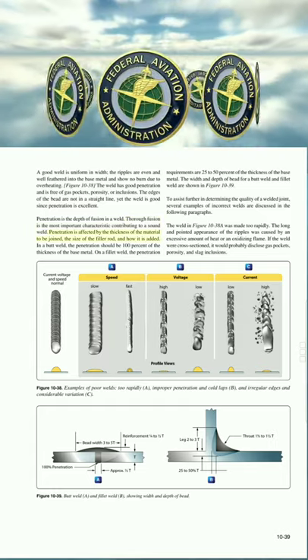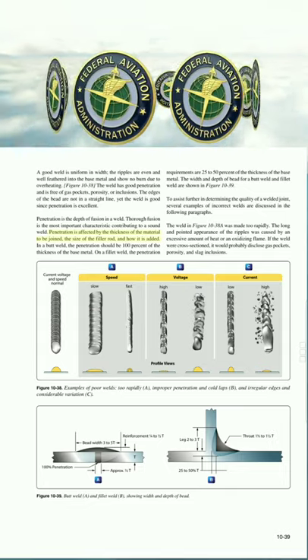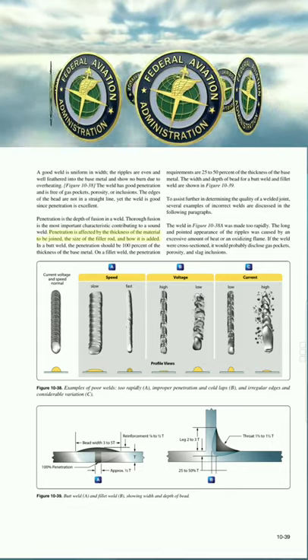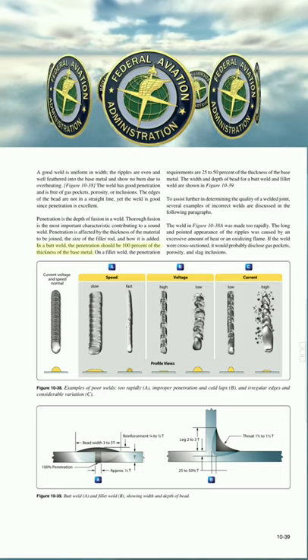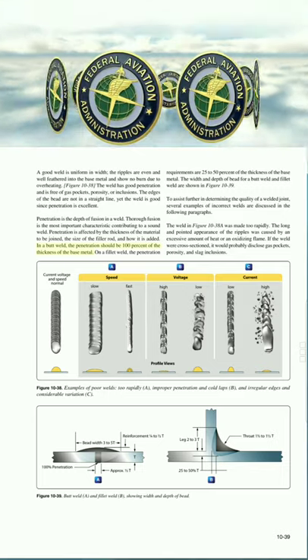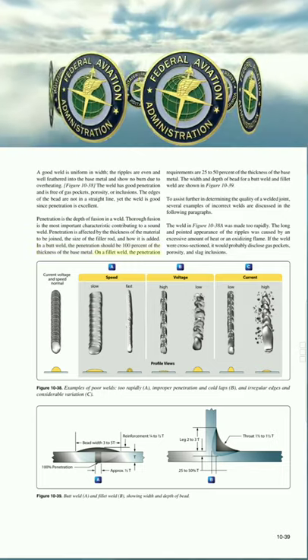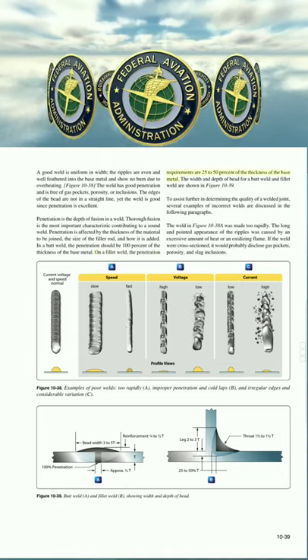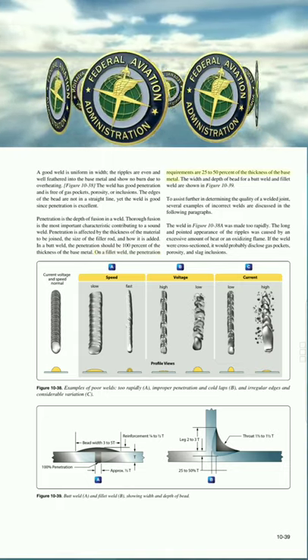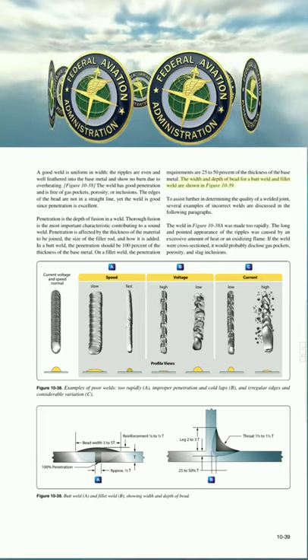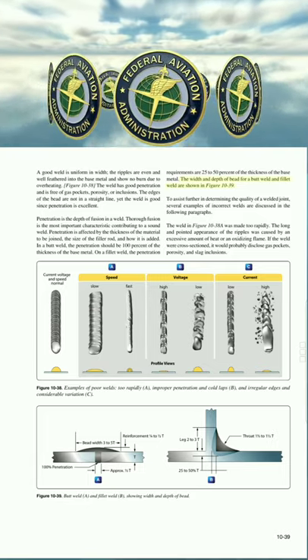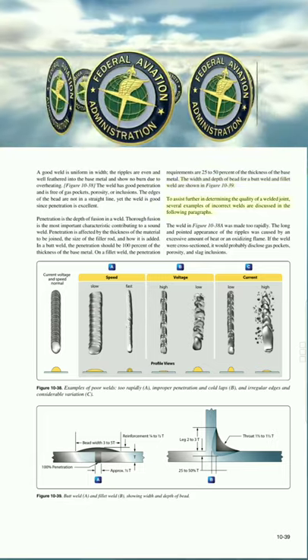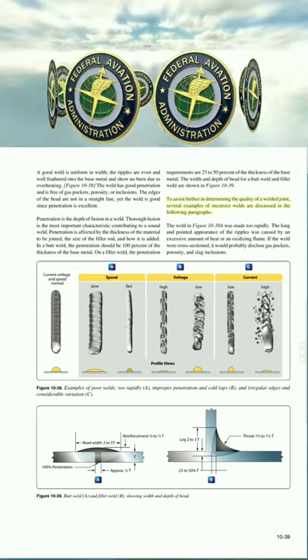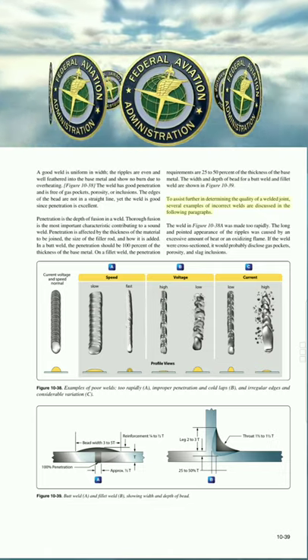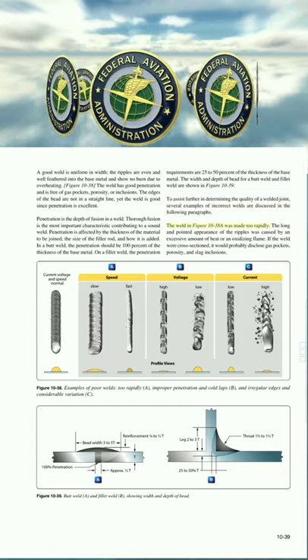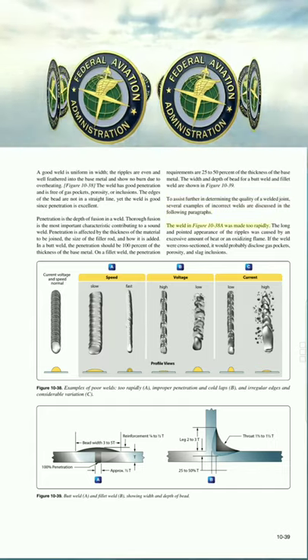Penetration is affected by the thickness of the material to be joined, the size of the filler rod, and how it is added. In a butt weld, the penetration should be 100% of the thickness of the base metal. On a fillet weld, the penetration requirements are 25 to 50% of the thickness of the base metal. The width and depth of bead for a butt weld and fillet weld are shown in Figure 10-39. To assist further in determining the quality of a welded joint, several examples of incorrect welds are discussed in the following paragraphs. The weld in Figure 10-38A was made too rapidly.